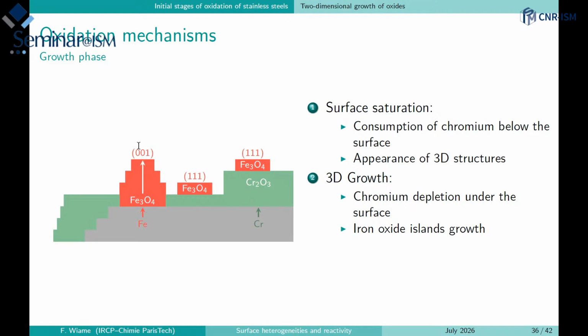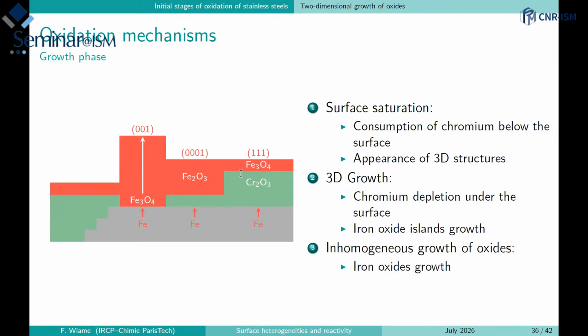some point when the chromium oxide layer is almost completely finished, then we have the diffusion of iron through this unpassivated area, where we can have some growth of oxide on top of the chromium oxide. And so the problem is that in this case, this pillar of chromium oxide is really the weak point where we can have some pitting, because there is no protection with the chromium oxide, and so the corrosion can penetrate from this point, and then once it has reached the material below, then it progresses, and these pits will grow under the chromium oxide layer, which is passivating some places, but not all the places. And so the idea is to try to see how we can improve.